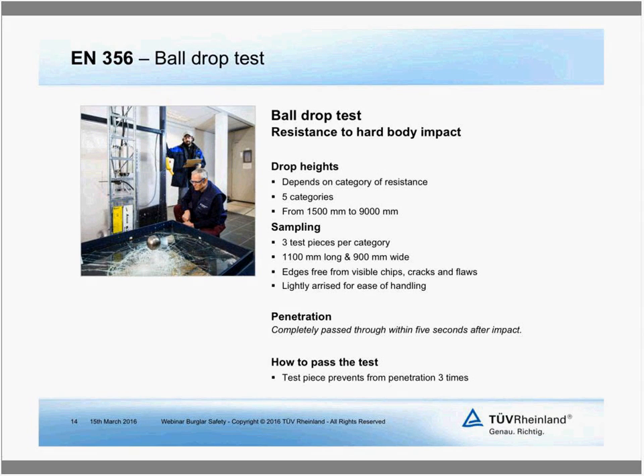Drop test is resistance to a hard body impact. The hard body impact being a steel ball of approximately 4 kilograms. The diameter is specified, and also well specified are the drop heights. Your impact is classified here, and the higher the drop height, the higher the impact will be. For every drop height, 3 impacts, 3 balls will drop in a certain pattern, and the pattern is also well described in the standards. And for the highest class at the ball drop test, even 9 balls, 9 impacts will be put on the glass sample.